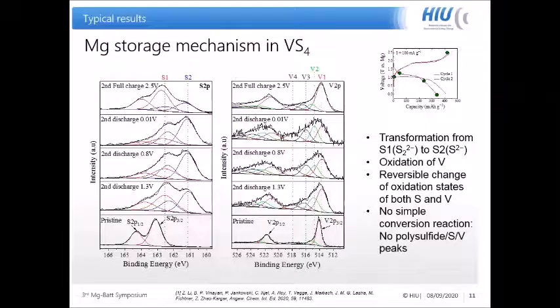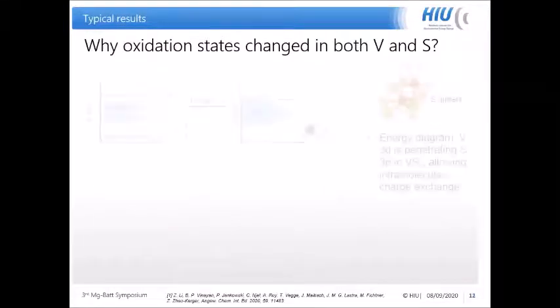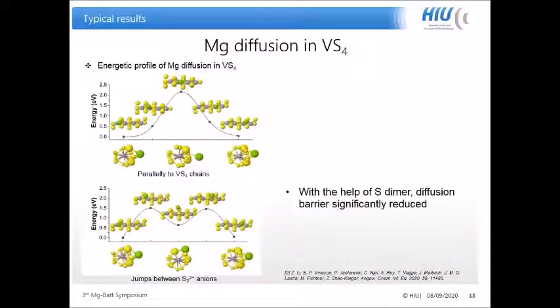There's one more here, which I can do now, from Sai Gautam Krishnan. Nice talk, Zhenyu. A 1.5 eV barrier is actually pretty high, way higher for a sulfide system! Did you calculate this with DFT? If so, do you have any idea of how magnesium intercalation can occur at the high rates that you mentioned? This is a good question, actually. I think this is mainly because we have considered the magnesium-sulfur bond during the ion diffusion. So that's why we have a higher diffusion energy calculated here.